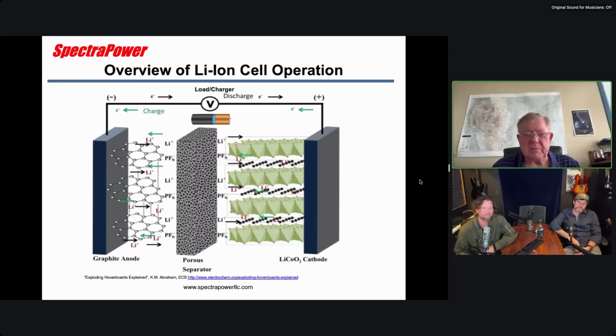A lot of times, most of these explosions are caused by particulates in the cell that are not supposed to be there, but inadvertently, due to errors in production, get into the materials. When they do, the lithium moving back and forth wants to plate onto those particles and form a dendrite. So the concept of solid state is, we'll put a solid sheet of hard material here so the dendrites can't puncture it, and you can't get a short. It's not a bad idea, but there are issues with it. Even if you have the solid separator, you still have liquid in the cathode. And people are usually kind of cagey about admitting it.